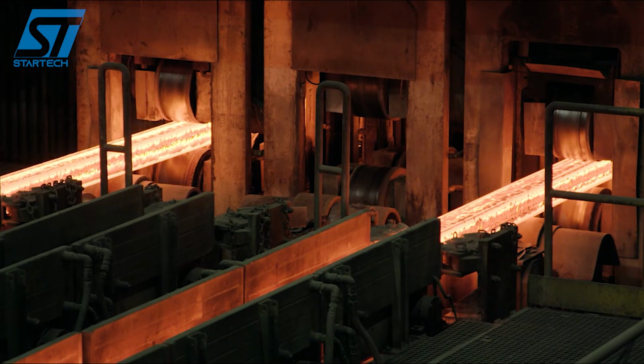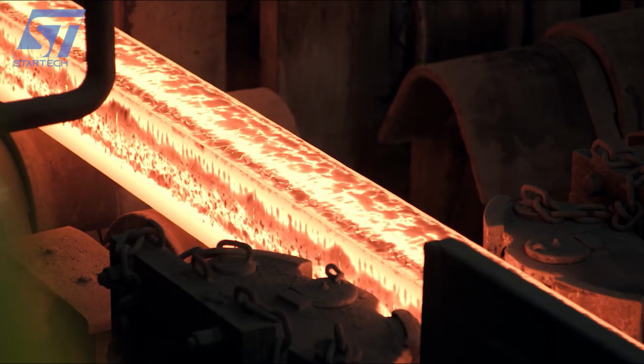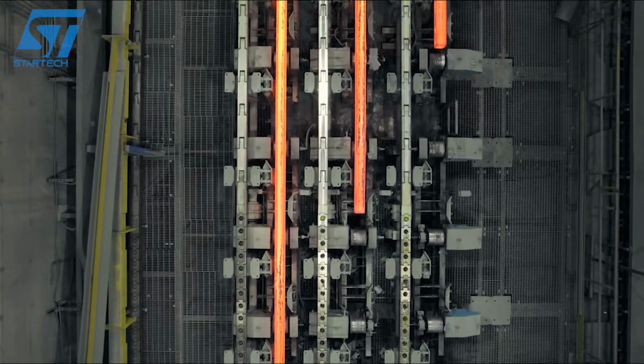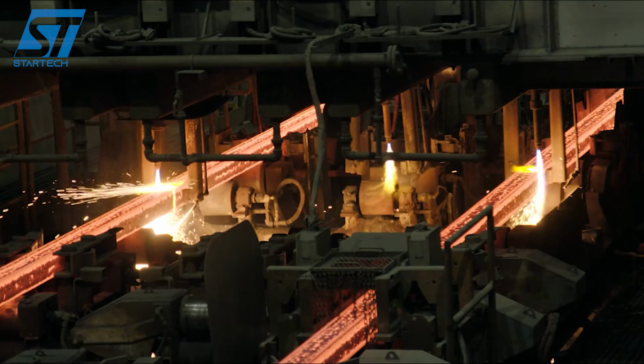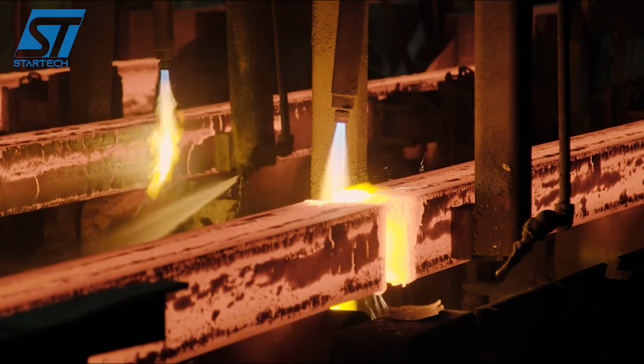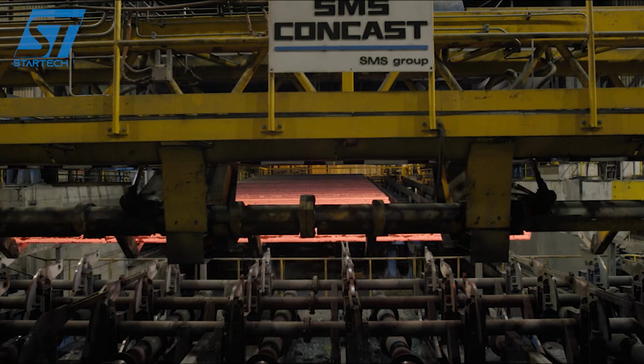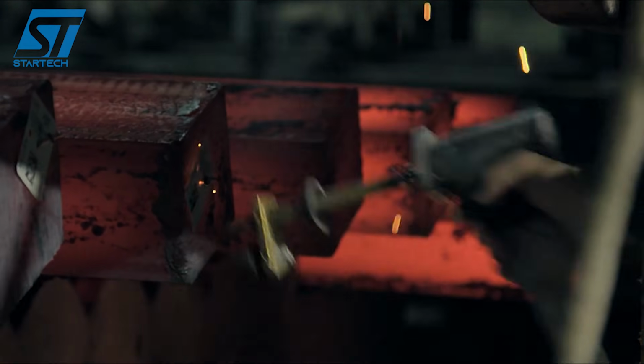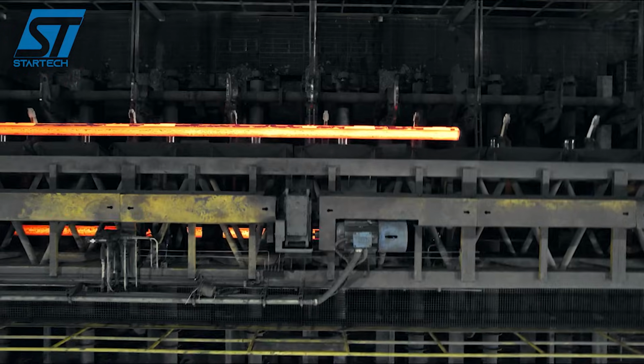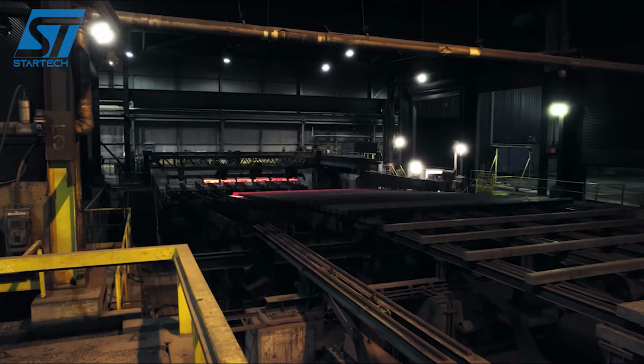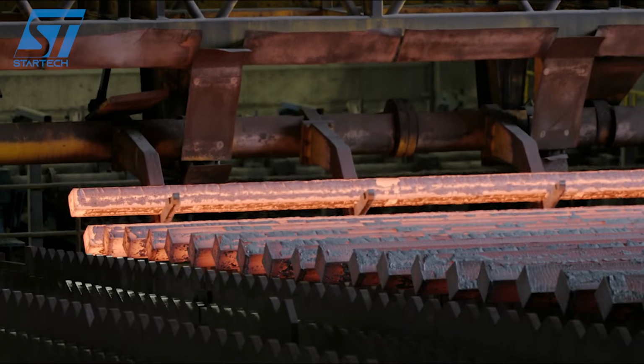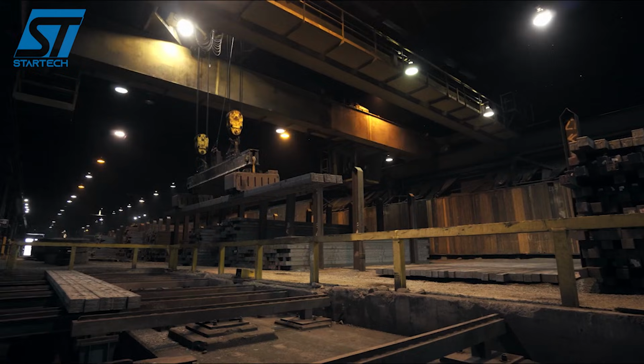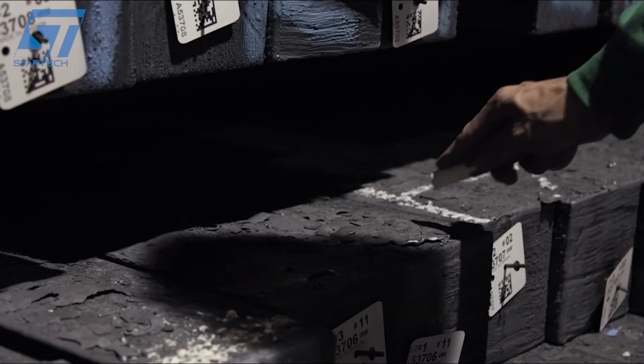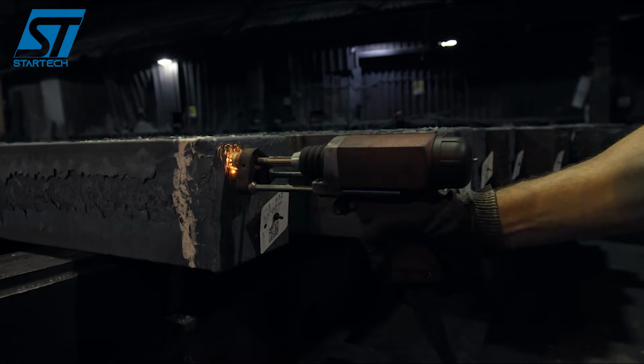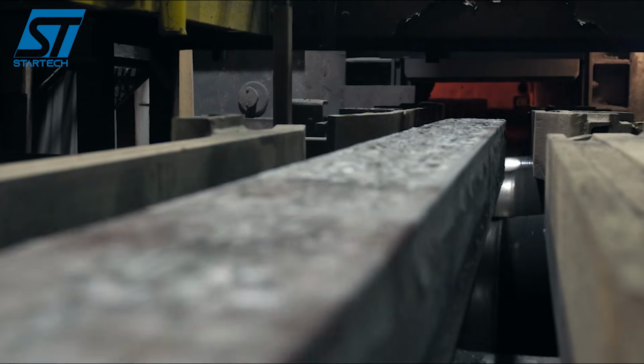Why reheat? Because steel at that temperature becomes workable, almost like very stiff dough, allowing the rolling mill to shape it without cracking. From there, the billet enters the roughing mill, a series of powerful rolling stands that progressively squeeze and elongate the steel. Each pass reduces the cross-section and increases the length. We're talking about a piece of steel that starts thick and square, being transformed pass by pass into a long, round rod. The process continues through intermediate rolling stands and finally through the finishing block, a high-speed rotating assembly that delivers the wire rod at its final diameter, typically between 5.5 millimeters and 20 millimeters.